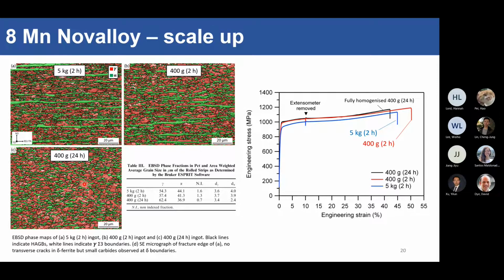This is the same steel that I was talking about for the cold rolling study. So if you nuke it for 24 hours, I can confirm that there's no more delta ferrite. So this 24-hour steel represents sort of the full capability of this steel. And if you look at the tensile curves here, you can see that even though you've got some delta ferrite, we've actually managed to preserve the very unique hardening behavior of these medium manganese steels. There is no reduction in elongation at all.